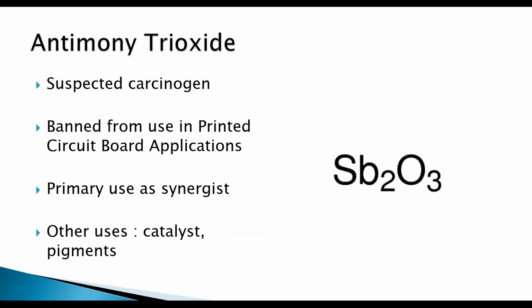Antimony trioxide, its use over the years has definitely declined. It still is used today. It is a suspected carcinogen, and so that has limited its use in new applications today. It's basically banned from use in printed circuit board applications, and the reason is that through the copper plating, antimony trioxide basically is a catalyst for the deposition of copper where you don't want it. So they no longer use it for that application because of the problems associated with it. It's primarily used today as a synergist for flame retardants. There are some other small uses for it in catalysts and pigments, but quite a few pounds of the material are still sold today.